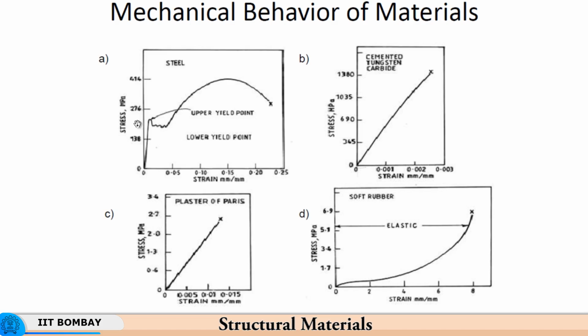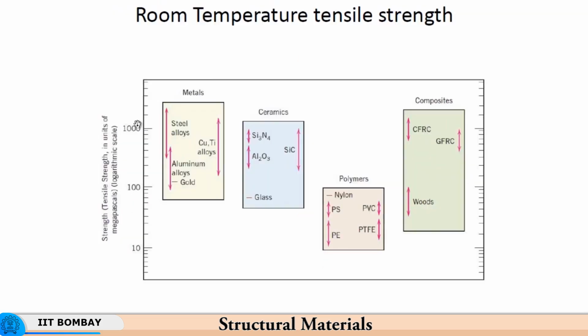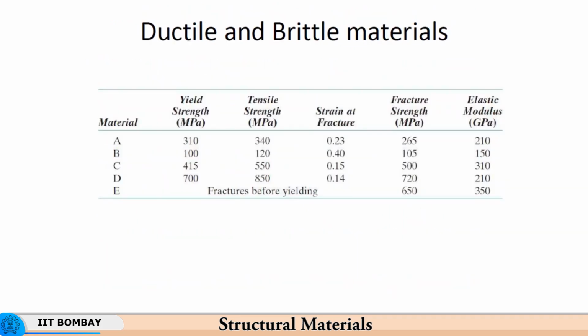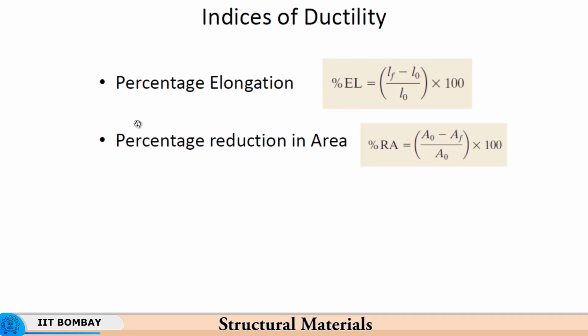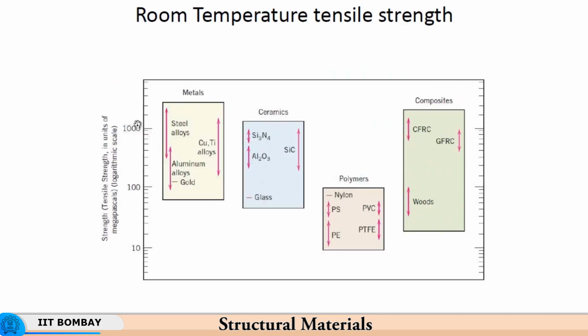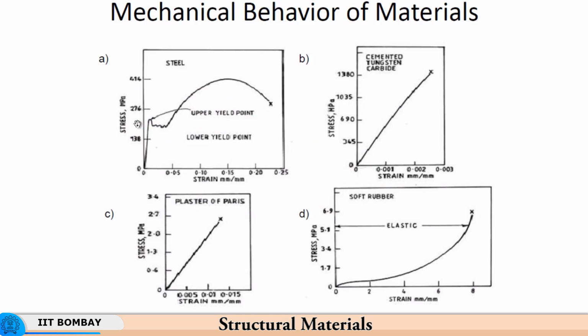So somewhere in between itself, so that you do not result in failure due to imminent localized necking. Actually you have diffuse necking here and then a localized necking over here. Here you lose the work hardening capability at UTS, and then you go down in capacity to withstand the load. So here, a higher value of n will represent high value of ductility. What it means is a large value of n will mean that the material has got greater uniform elongation. So this point shifts to a higher elongation. That is what it means by having a higher value of n.